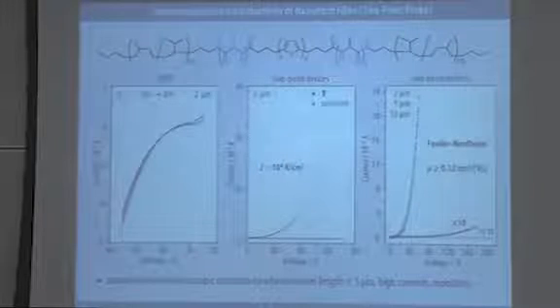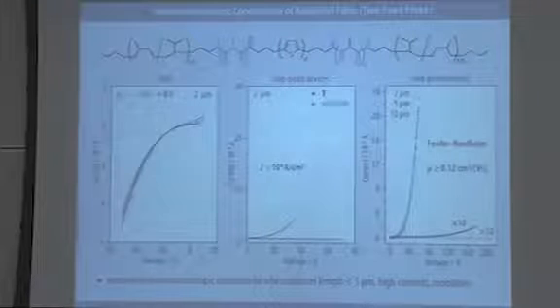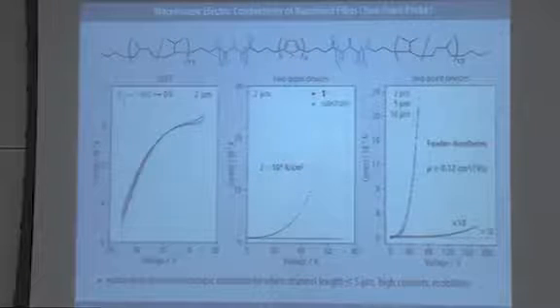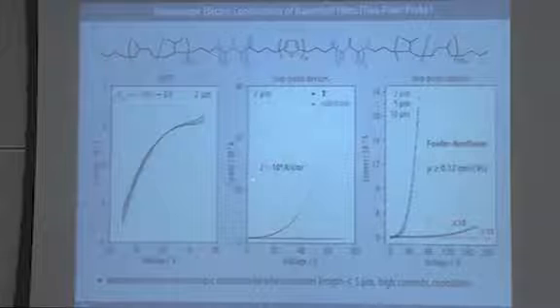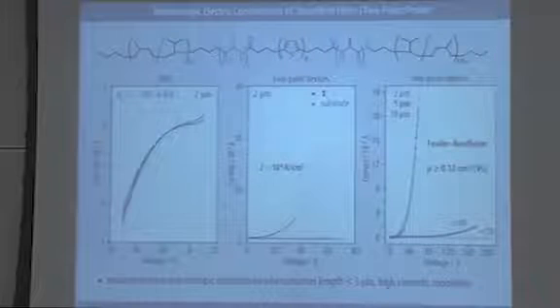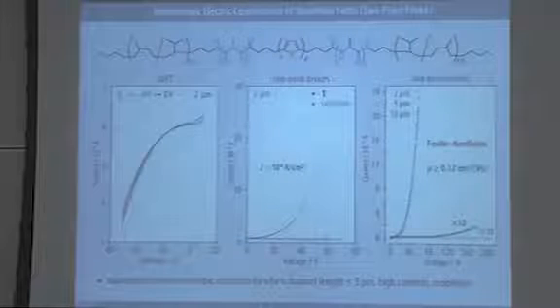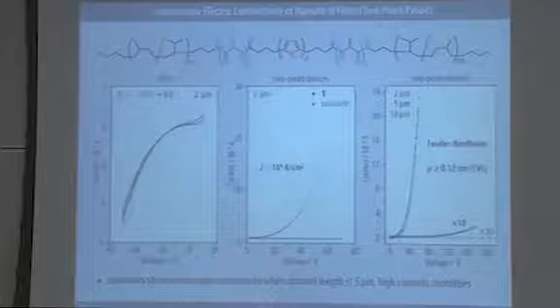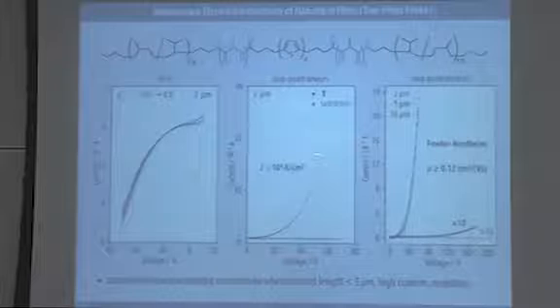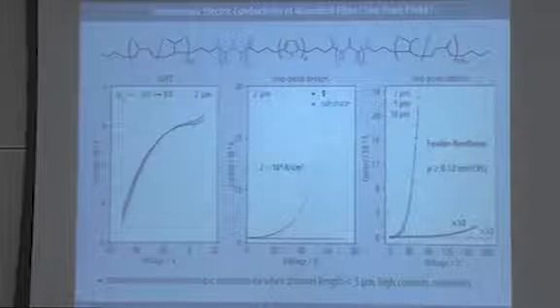So what it means to us is that charge transport is possible if a single nanofibril is contacted by the 2 gold electrodes, but it becomes impossible if the charge has to hop from one nanofibril to another one. The observed currents on the order of nanoampere may seem small at the beginning, but I need to tell you here that we actually counted from the AFM images the number of fibrils between the electrodes, and it's roughly 100. Even if it were 200 or 300, it wouldn't really matter. It translates into current densities that are exceedingly high inside the nanowires, on the order of 10 to the 4 ampere per square centimeter.